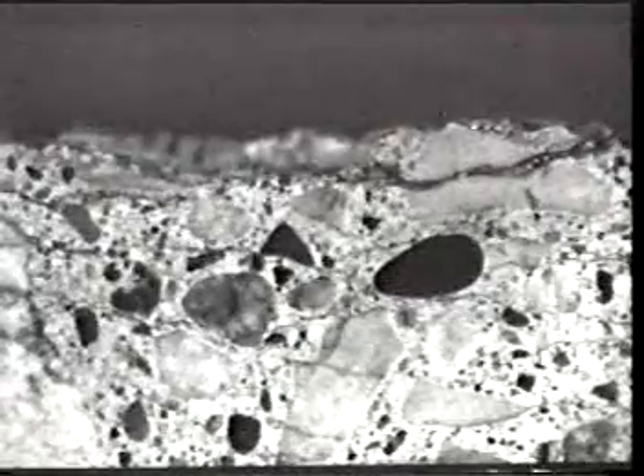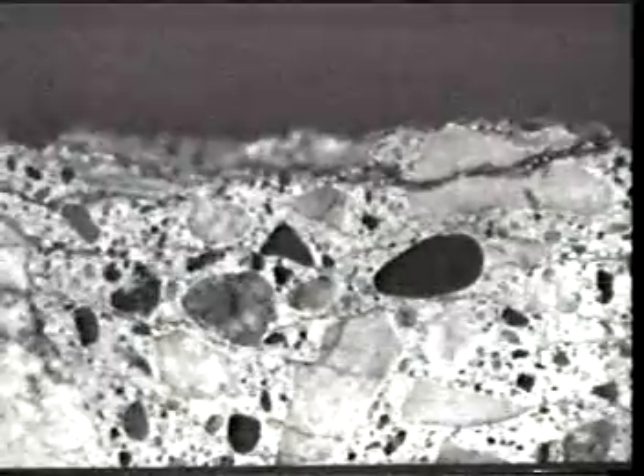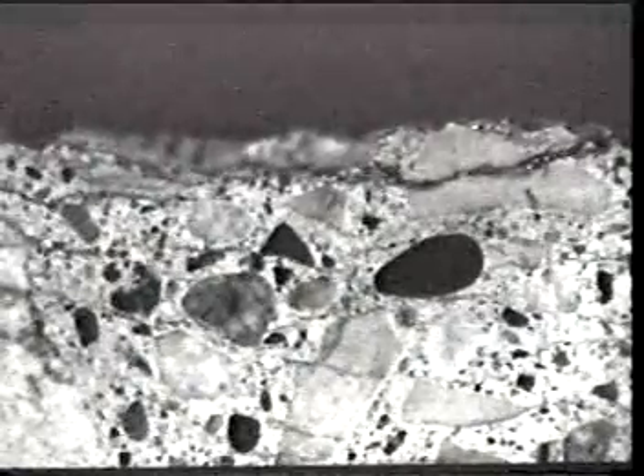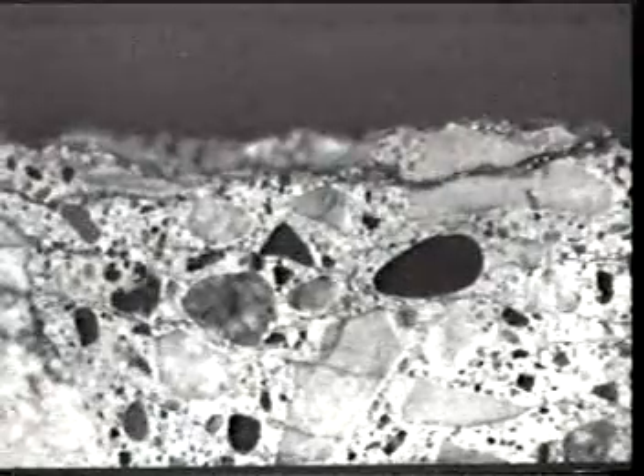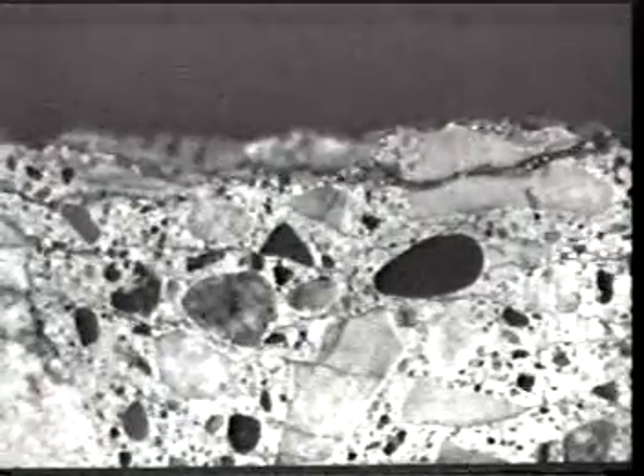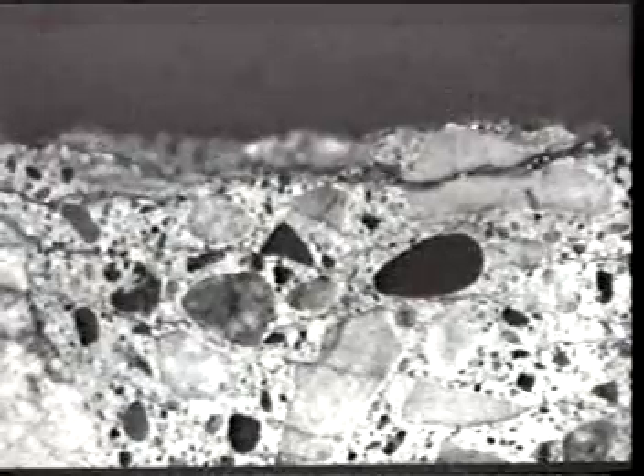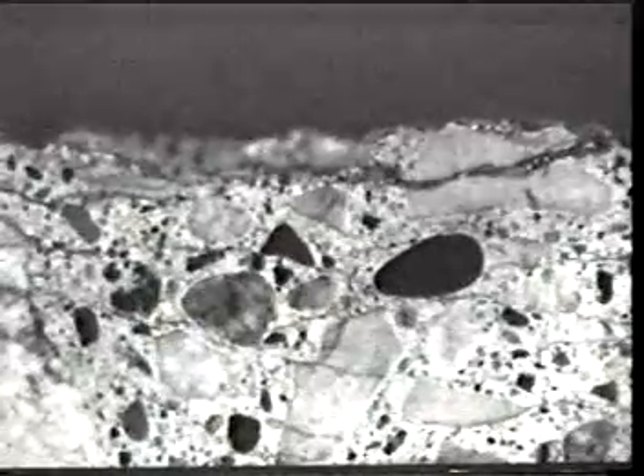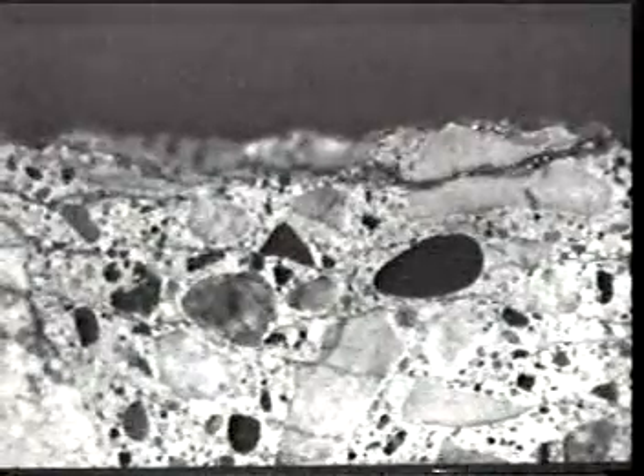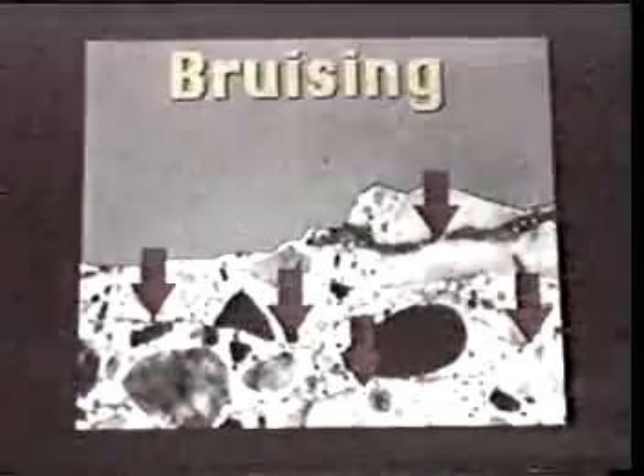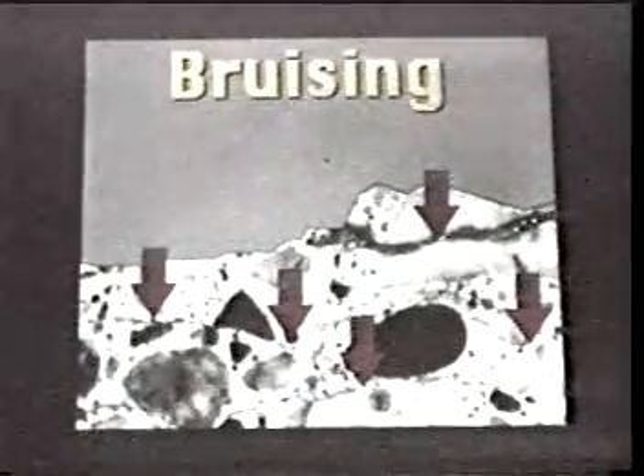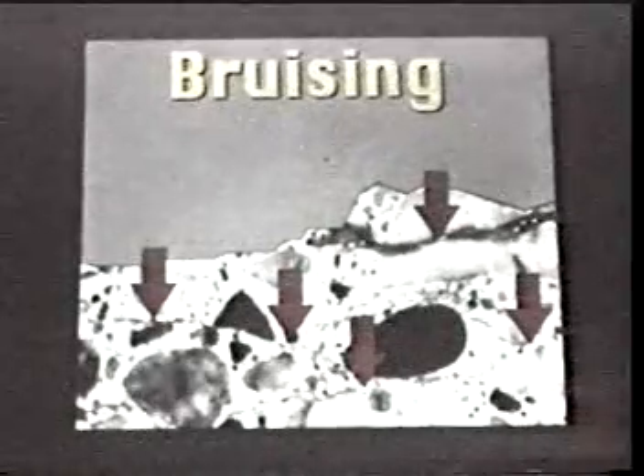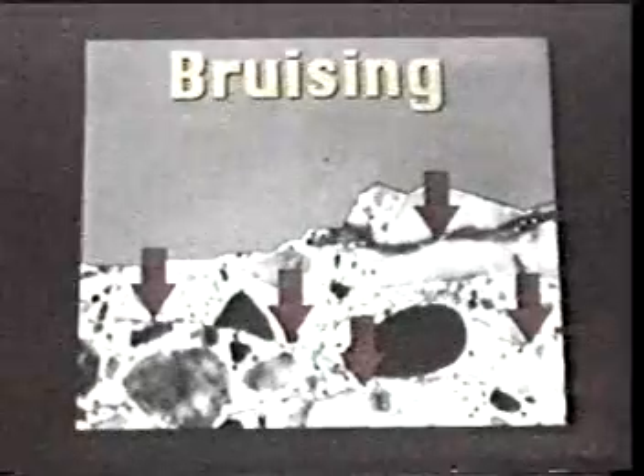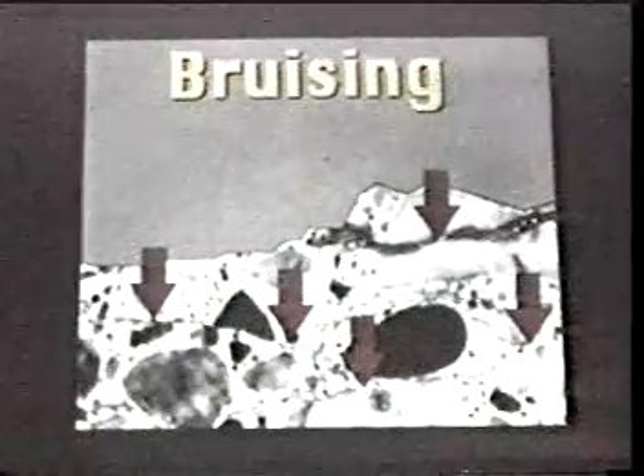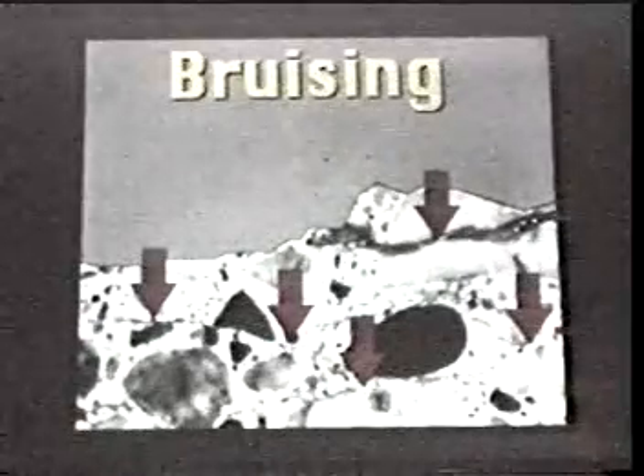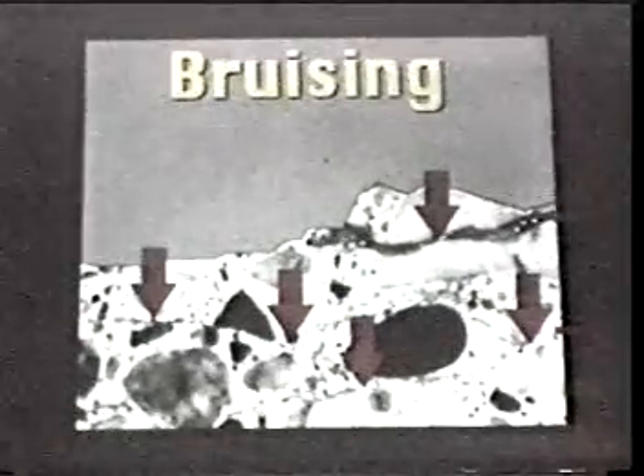And here you see this under serious magnification, but it is usually not on the macro level. On the macro level, it's almost impossible to see after the final cleaning, but it is on the micro level. You have all this horizontal fracture or micro cracking and all imperfections which very much affect the development of bond and the strength of the bond. What is shown here is bruising, and usually, if you are not barbarically removing concrete, it doesn't affect probably more than 1/8, 1/4 of an inch of the concrete